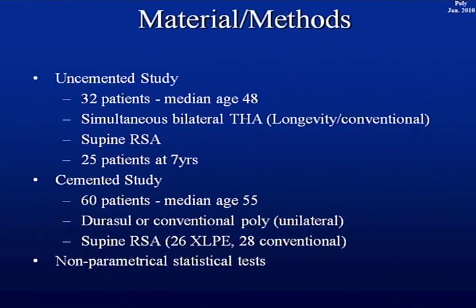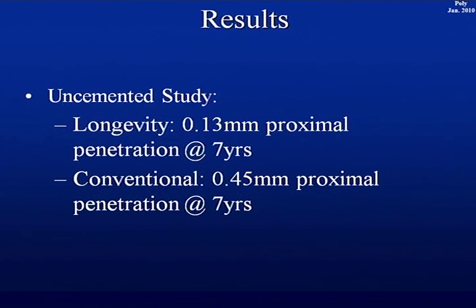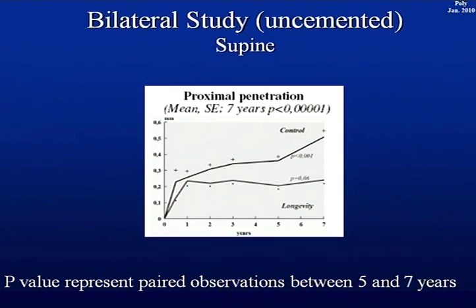32 patients in the uncemented, simultaneous bilateral total hip, and 25 were evaluated at 7 years. In the cemented study, 30 patients in each group as well, and Durasul or conventional poly, supine RSA, and the result was a 0.13 millimeter proximal penetration at 7 years in longevity compared to conventional 0.45, which is fine. That's what we would expect.